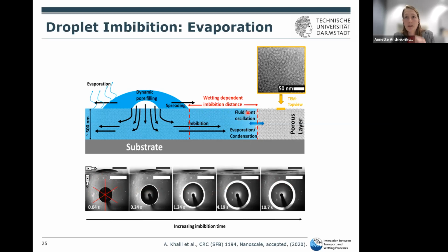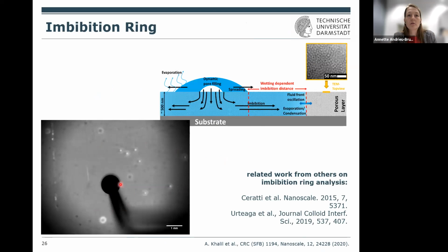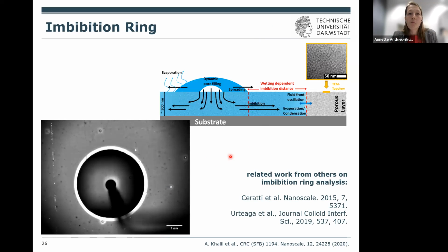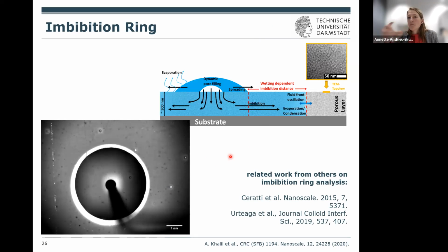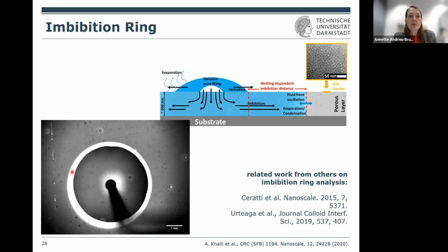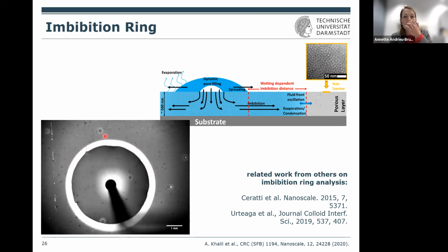And there's a second thing happening, excuse me, that this fluid front oscillates, and you will see this in a kind of breathing movement in the video. So please just focus on this video, and what you see is that the droplet is deposited onto such a mesoporous film. So you see this imbibition ring, and maybe if you look closely, you see that it's slightly moving here at the front. So to learn something on the influence of this wettability on this imbibition ring, you can now analyze the width and the oscillation.